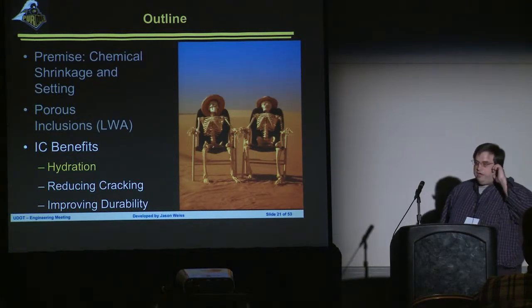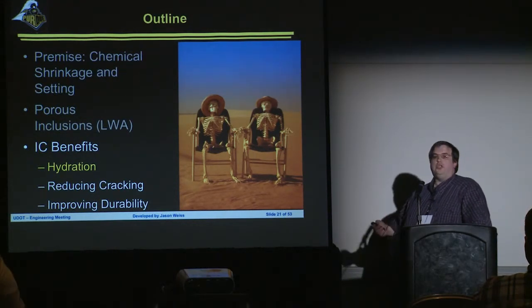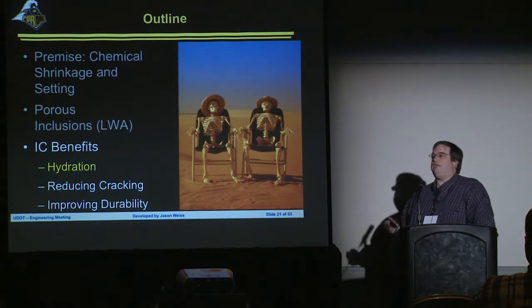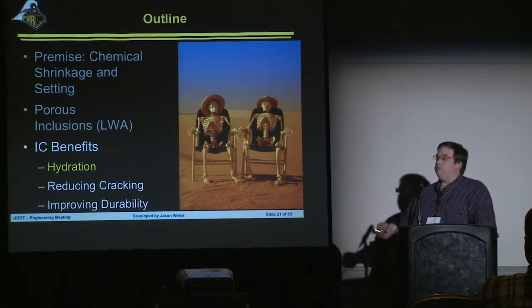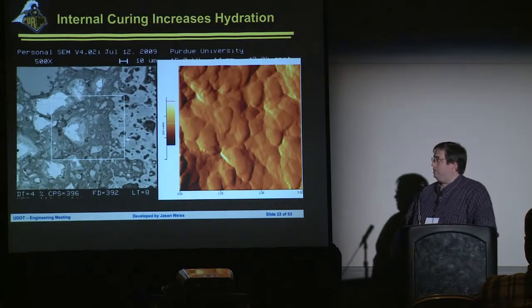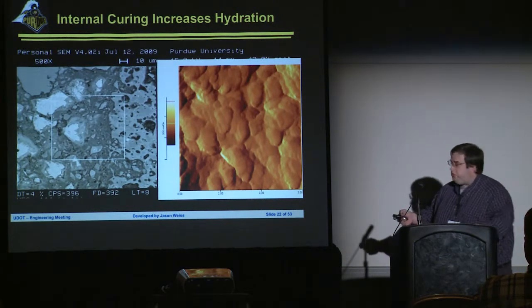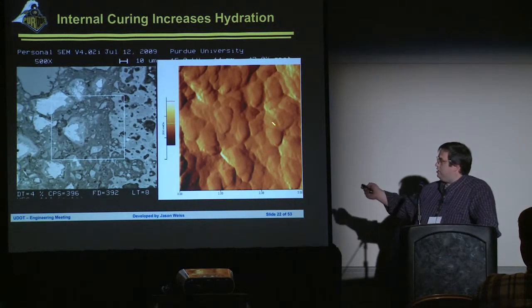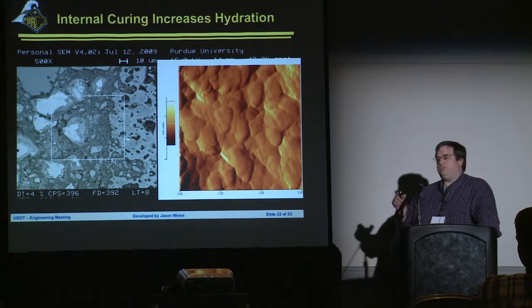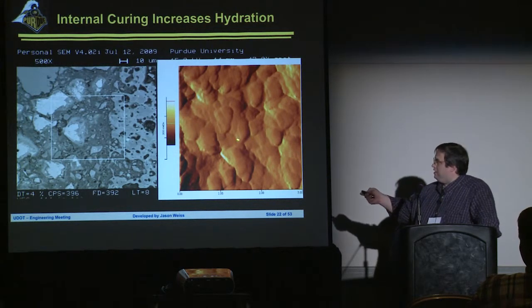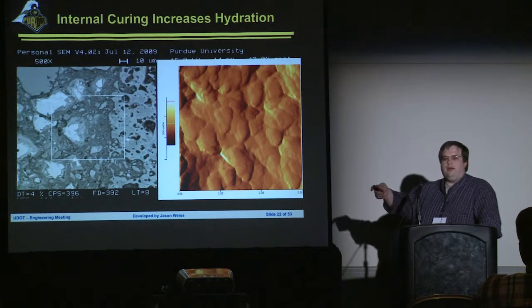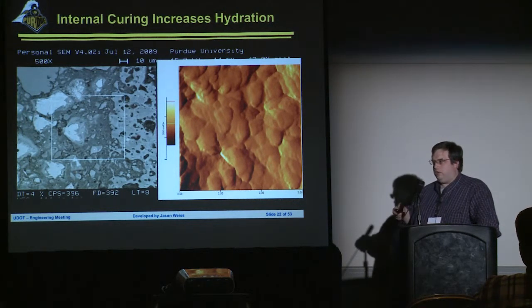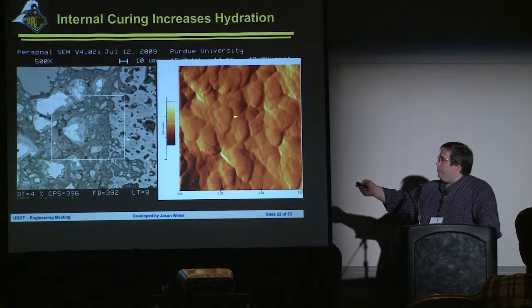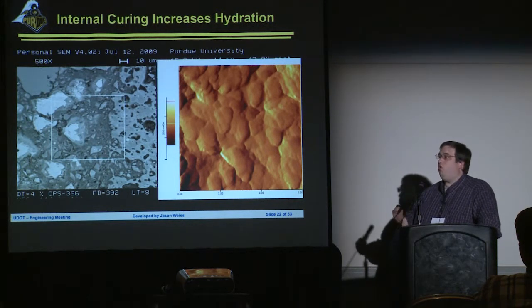All right, so what are some of the benefits? All right, obviously hydration is a key issue. If you do not keep the system hydrating, all right, you've got some big problems in how that system is going to perform over its life. All right, now, these pictures here are essentially two different types of images. This is a look at cement paste on the nanoscale, where essentially you're looking through a microscope that essentially interacts with the paste by dragging a very expensive record player needle across the top of the surface. And what you can see is we get a very, very dense system when we've got a lot of water inside of there to hydrate the overall system.